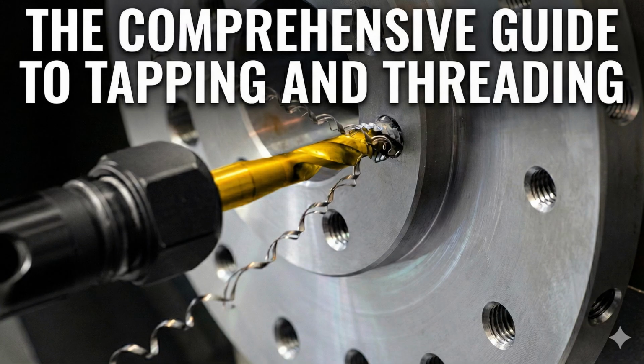Why is the thread actually stronger when it's formed? It really comes down to two things: work hardening and grain structure. Okay. When you use a cutting tap, you're literally slicing across the material's grain structure, which can sometimes weaken the flank of the thread. But with a forming tap? With a forming tap, the material is compressed and forced to flow. You're essentially work hardening the surface as you create it. This compression leaves behind what's called residual compressive stress, which dramatically improves the thread's fatigue life and its overall strength.